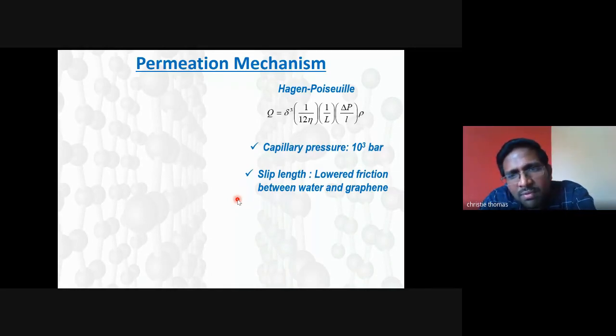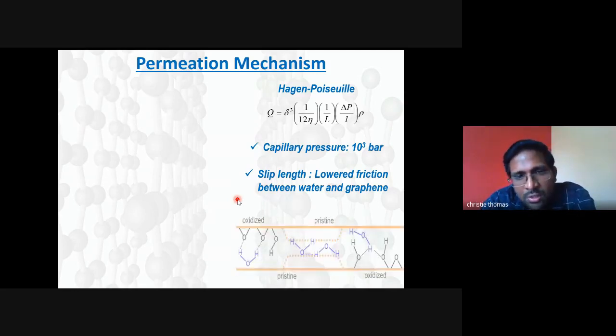Okay, but when you introduce slip length as well as a capillary pressure of 1000 bar, you get experimental and theoretical values that are almost close. So it has been assumed that there is a huge capillary pressure inside these graphene nanocapillaries, as well as the slip length. I already talked about slip length. That contributes to the fast permeation of water.